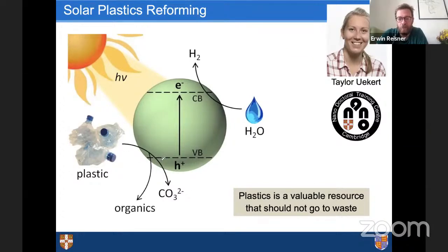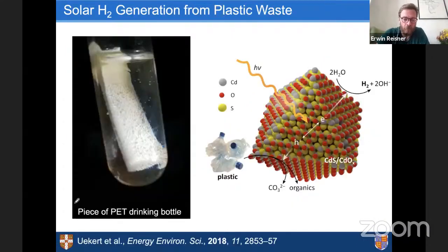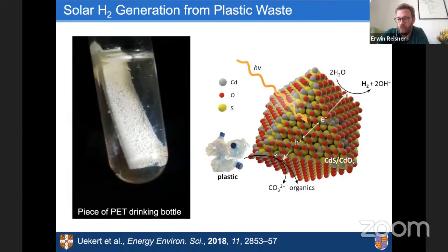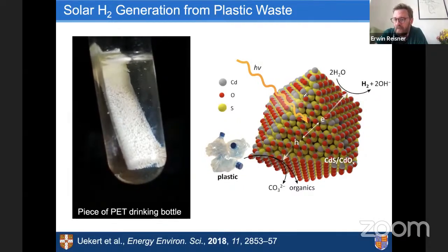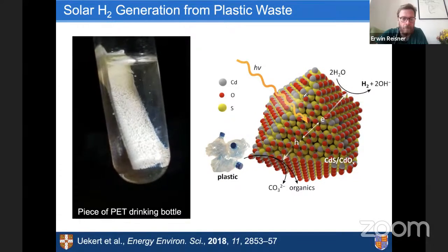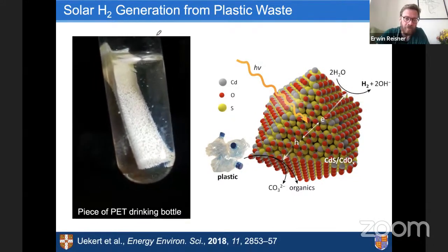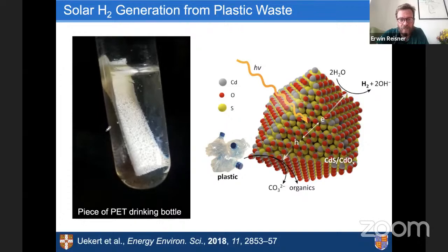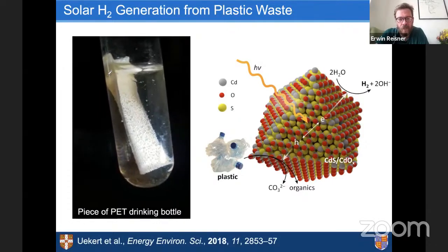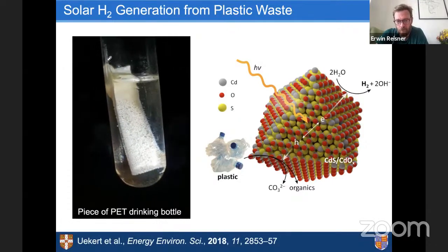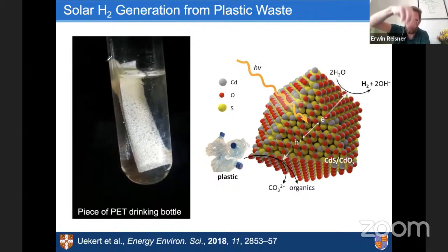Instead of feeding now the biomass or even the water oxidation originally, the idea is just to use plastic waste as a way to source electrons with the hope to form some organics on the way to produce the hydrogen. And here again, the first system we introduced was the cadmium sulfide under the alkaline conditions forming the oxide shell. And I will just talk about this little video here on the left. So what you see here again is this test tube. And now there's a slice of PET water bottle, right? That's just being put into the test tube.